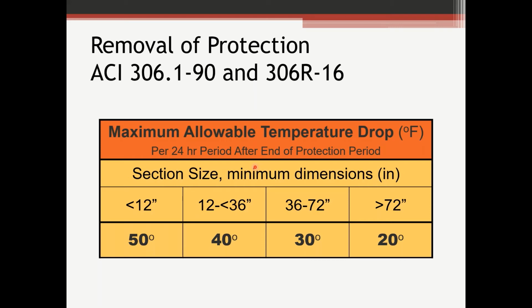But the allowable temperature drop is dependent on your section size. So that 6-inch slab or 8-inch foundation wall or something similar to that, less than 12 inches, no more than a 50-degree temperature drop. You can see as the minimum section size gets bigger, the allowable temperature drop decreases. These larger sections can really be more susceptible to thermal shock, so you want to make sure that you're not exposing them too quickly.